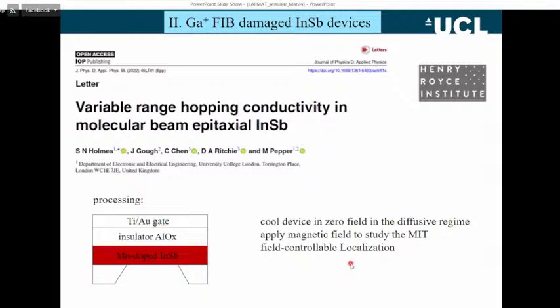And the original idea was to apply magnetic fields. Now, the electronic g-factor in this material is very large. Applying magnetic fields makes a very large difference to the conductivity. The conductivity can go over to hopping in a magnetic field. So that gives us a kind of tunability of this hopping effect.